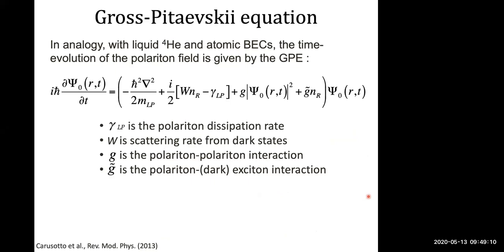The way we model the dynamics of the condensate, in a way that allows us to include this nonlinearity, is using the Gross-Pitaevskii equation, in analogy to what you would do to model an atomic BEC. And one change to the usual Gross-Pitaevskii equation is that we will also use a term which accounts for pumping and dissipation of the condensate, as well as a term which accounts for interaction with the reservoir. Okay, so this is a nonlinear Schrodinger equation. This G psi squared term is the nonlinear term, where G is the effective polariton-polariton interaction strength, nothing to do with the coherent coupling G from earlier.